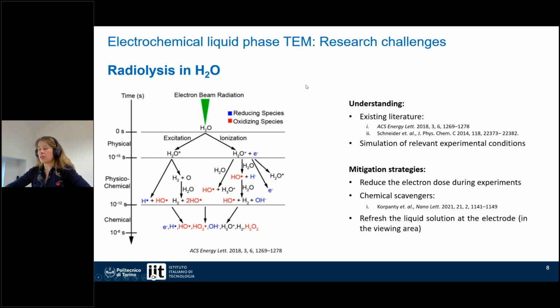The first, as I said, is the fact that we use the electron beam to probe the material, and we do it in a very small region. And while we probe the material, some of the electrolyte will decompose in a process called radiolysis. The water molecules are broken and they recombine in a series of steps, and they form many various radicals and species containing hydrogen and oxygen. And at the end of all this, we can have creation of some bubbles, which will possibly then stick in the experiment.